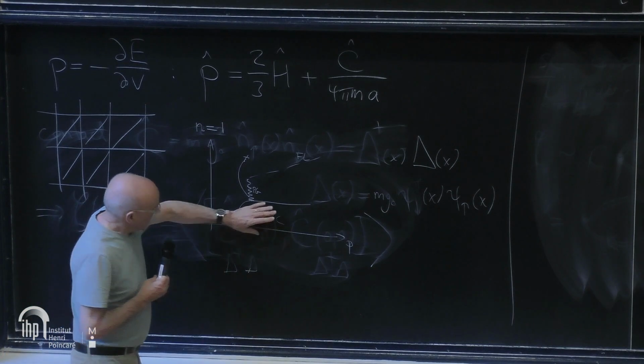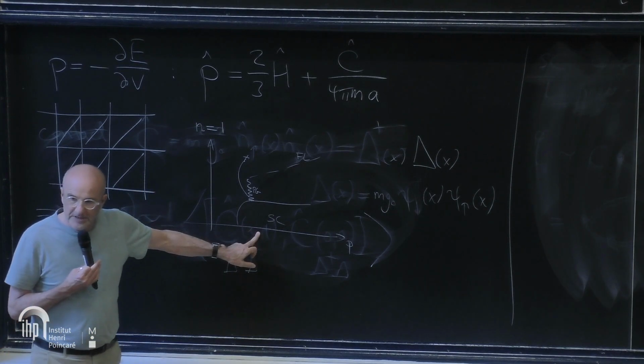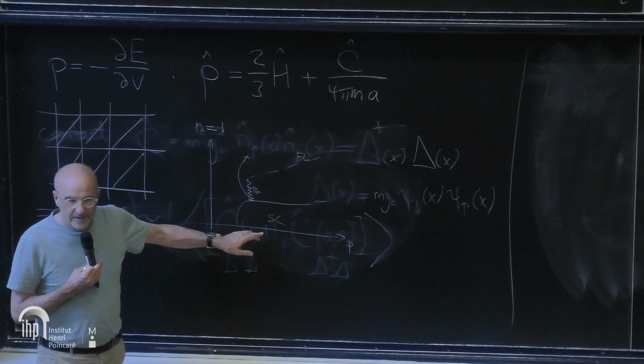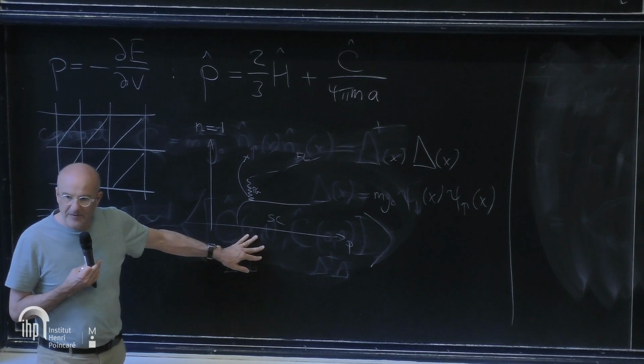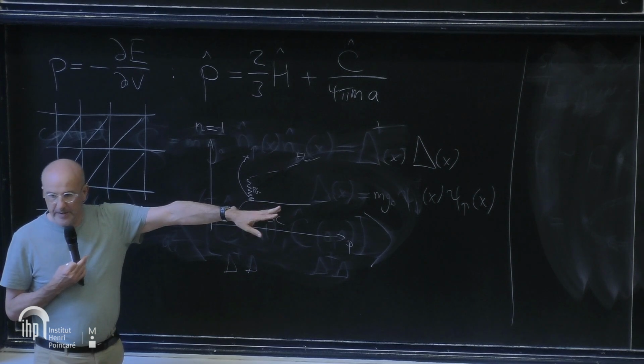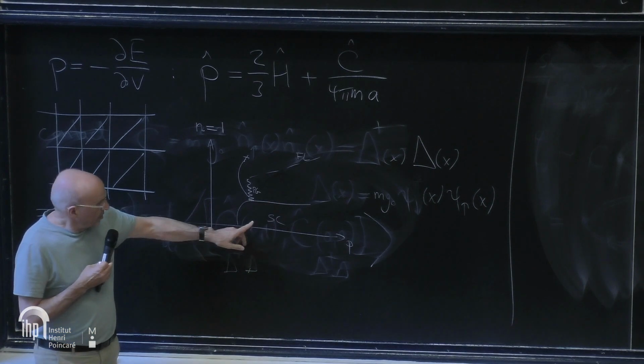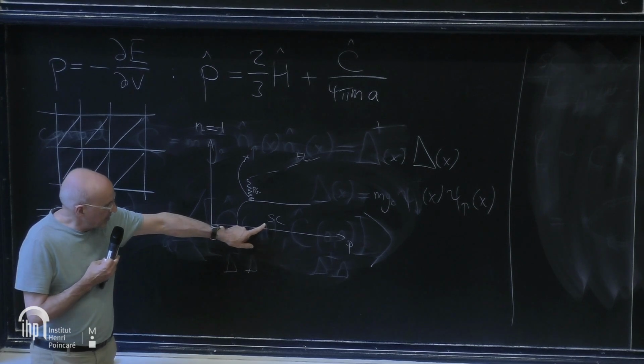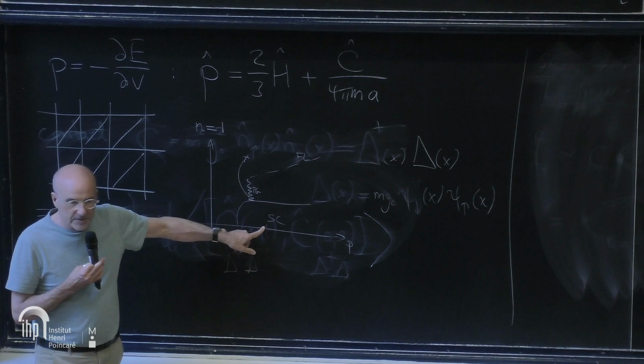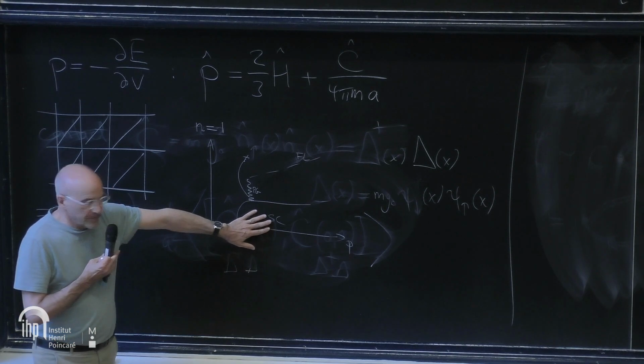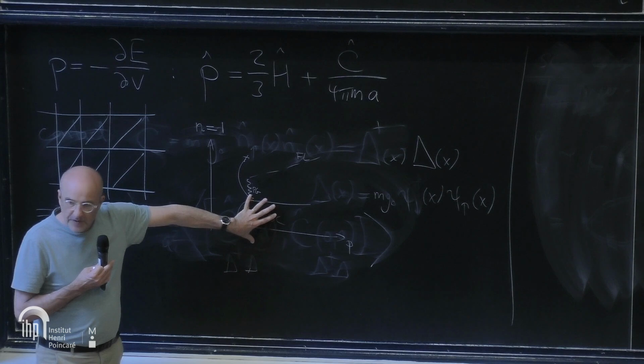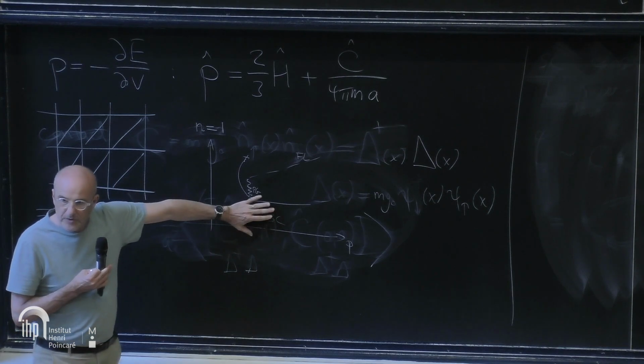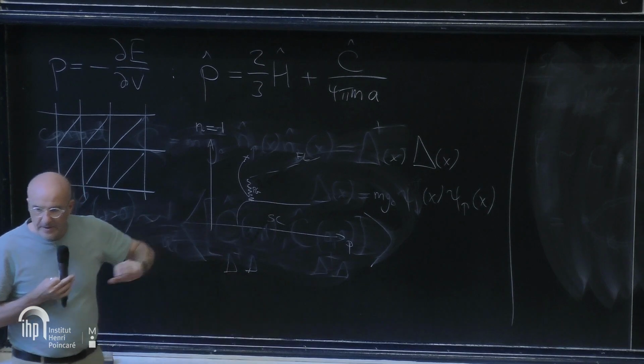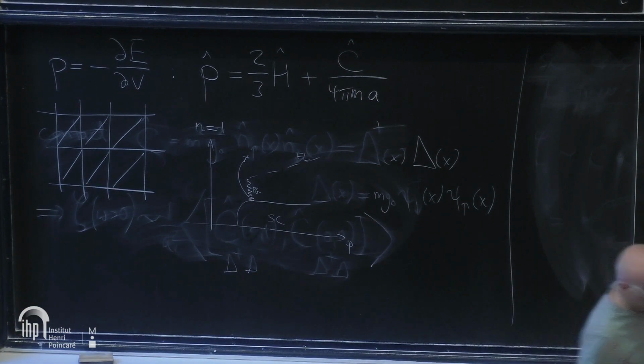So now the fact that this model can have a superconducting ground state, I would say is not established to the same level of rigor as the very detailed recent studies on square lattice Hubbard. But we recently have a paper on this, and André-Marie Tremblay in Sherbrooke has done a lot on that in past years. If you do cluster DMFT studies on this sort of lattice, you do find indeed a superconducting ground state of D-wave symmetry.